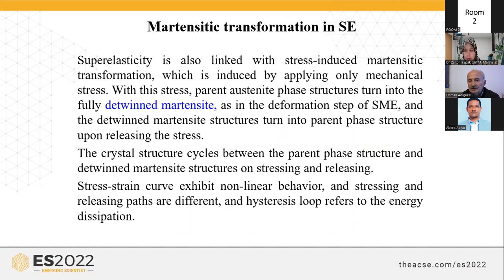Superelasticity is also linked with stress-induced martensitic transformation, which is induced by applying only mechanical stress. With this stress, the parent austenite phase structure turns into detwinned martensitic structures in the deformation step, and detwinned martensitic structures turn into the parent phase structure upon releasing. Crystal structures cycle between parent phase structures and detwinned martensitic structures on stressing and releasing. It is important that the stress-strain curve exhibits non-linear behavior, and the stressing and releasing parts are different; the hysteresis loop refers to energy dissipation.